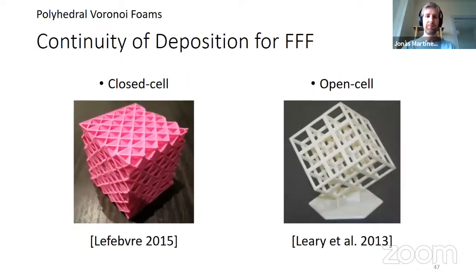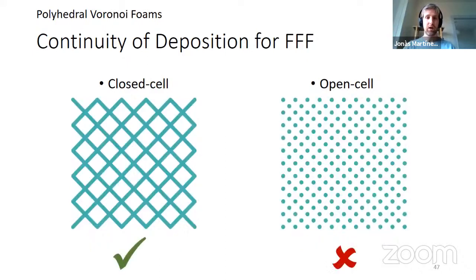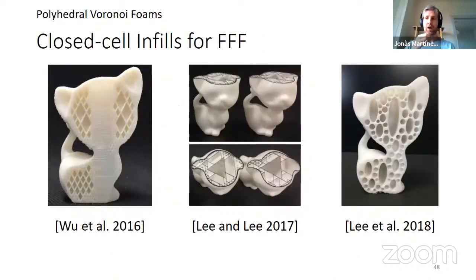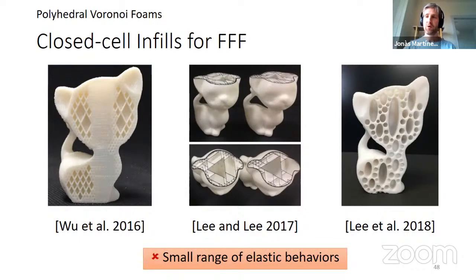So there's been some work on doing structures for fused filament fabrication. Some of them are closed cell, others are open cell. We favor using closed cell mostly because when you do the deposition, you can get a continuous path. And on the open cell, you have to jump from one to another, which will probably pollute the print a lot. And regarding closed cells for fused filament fabrication, there was already previous work on some families, but what they had in common is that they span a small range of elastic behaviors, because they were just a single family, and we wanted to have a wider parametric family.